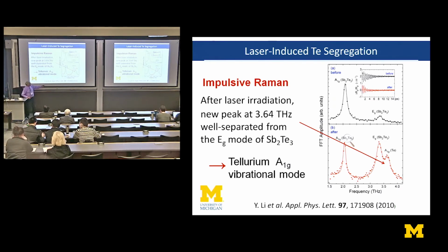And we can use that separation across the van der Waals gap to produce a layer of tellurium separate from the regular structure. And it's correctly identified here as an A1g optical phonon. So these kinds of measurements done during the processing are really crucial, because otherwise, how would you know what's going on? You do something to the material, but you don't know what it is. Here, this gives you really good microscopic information.